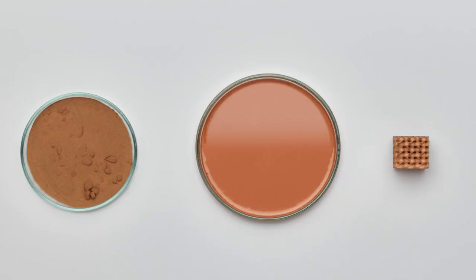In our process, we start with ceramic or metal powders with a fine grain size. We mix the powders with a liquid, UV-sensitive resin, and this feedstock is called slurry. When UV light is applied, the slurry cures to a stiff polymer, and this holds together the ceramic or metal powders. With help of a 3D printer, we can build virtually any shape by adding layer after layer.